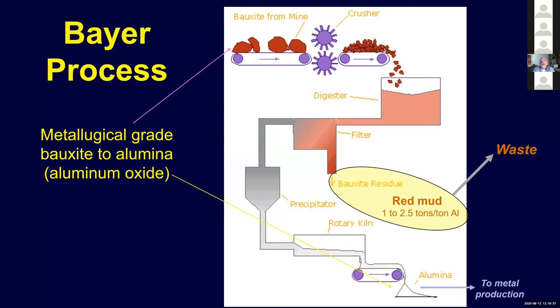And in that process, as you extract the aluminum, you're left with iron, which actually doesn't dissolve. And that comes out as a bauxite residue in the system, which forms something called red mud. So you get roughly 1 to 2.5 tons of red mud per ton of aluminum produced. That material gets separated out and goes to a red mud lake, which I'll show you pictures of in a moment.